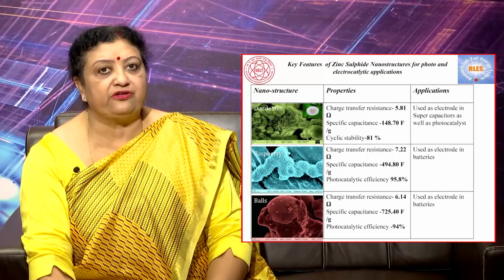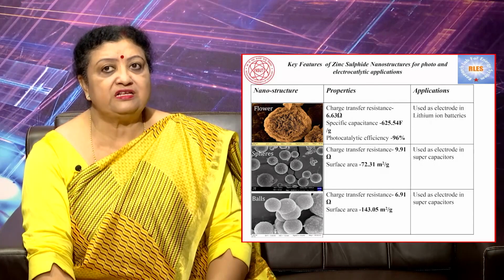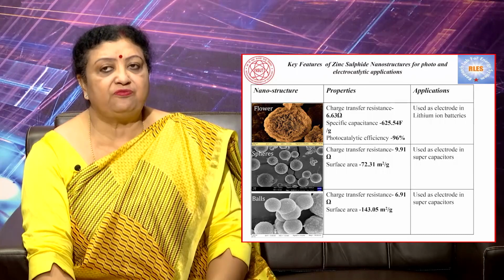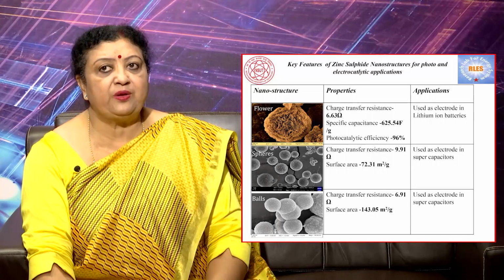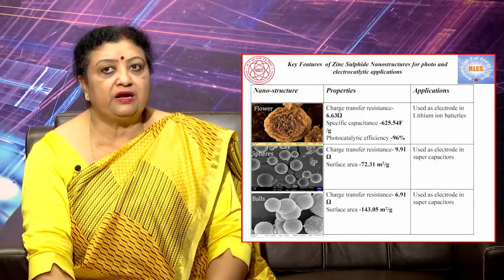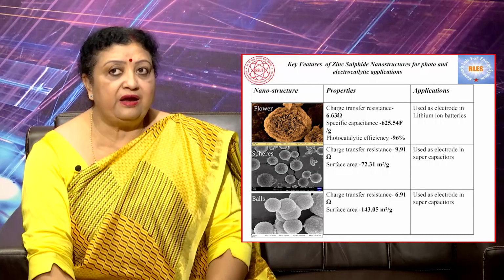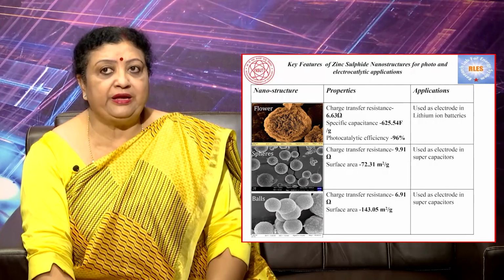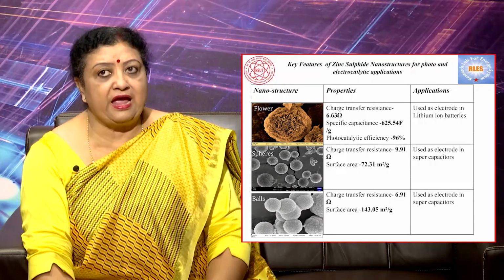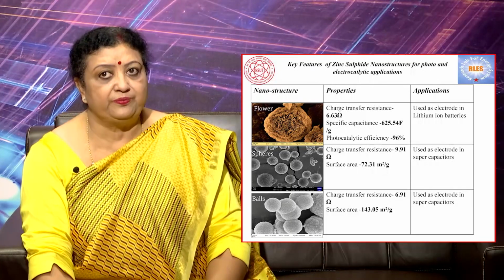Flower-like ZnS nanostructures also have charge transfer resistance of 6.63 ohms, specific capacitance 625.54 farad per gram, photocatalytic efficiency is 96%, and the potential application is as electrodes in lithium ion batteries.